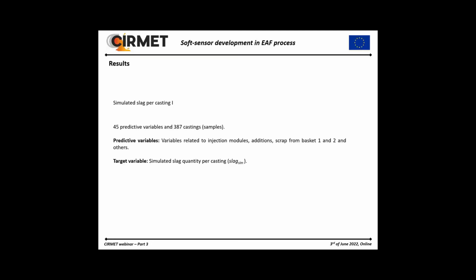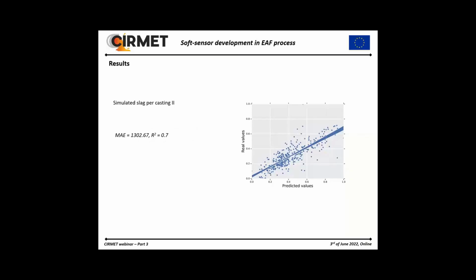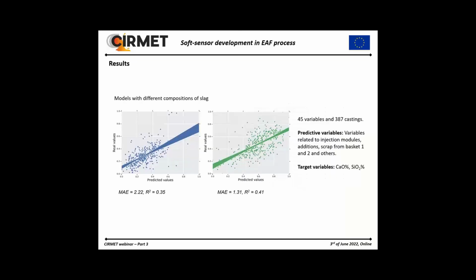Here we have a reduced set of castings, because not for all the castings the composition of the slag was performed. In this case, we employed the gradient boosting regressor with 5-fold cross validation, and you can see there the error obtained, the MAE, and also the coefficient of determination.